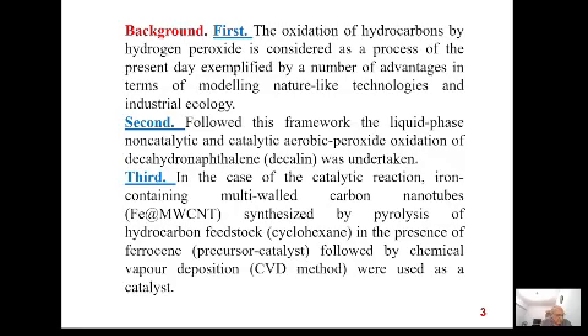Following this framework, the liquid phase non-catalytic and catalytic aerobic peroxide oxidation of decahydronaphthalene, that is decalin, was undertaken. The combination of aerobic, involving molecular oxygen, and peroxide, that is hydrogen peroxide or organic hydroperoxides, suggests a process where the peroxide is used either as a primary oxidant or, more commonly, as an initiator in the presence of molecular oxygen or air.